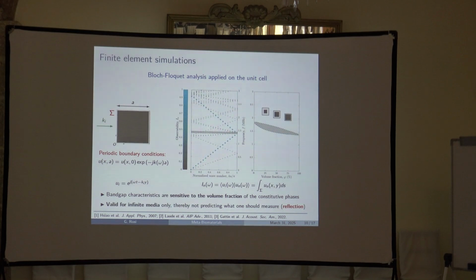So once we validate this for an infinite medium, we still have the problem that in experiments and in our application, we will have a finite specimen with 10 cells, 20 cells, and we'll have viscoelasticity. So in order to validate this, and also because we want to play with the reflection coefficient, there is no way to compute the reflection coefficient from Bloch analysis. So we did a finite element simulation in harmonic regime where we consider perfectly matched layers, an incoming plane wave in water, our specimen, which is a finite specimen, and then we wanted to measure the reflection coefficient.